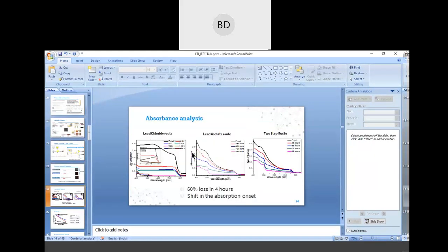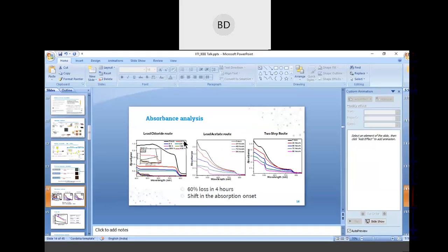If you see this film, the aging time is proportionate. The only thing is, I have not indicated the values, the observations which I've taken at 4 hours, 8 hours, 20, like that for these two, because there was no significant difference, or it was too many data points which did not have any significant value. So I have not used those data points here, but I have used the data points here. The aging time is the same throughout. We have taken all the characterizations for all the films at the same aging time.